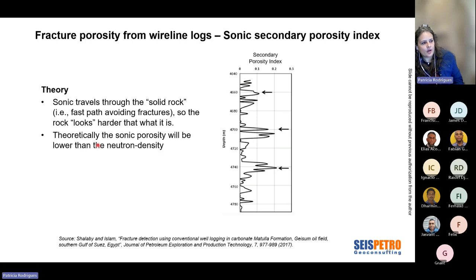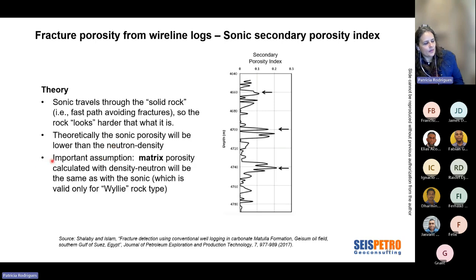Theoretically, the sonic porosity will then be lower than the neutron density porosity in the presence of fractures. It will also be valid if you have vuggy porosity as well. So anything that is isolated, the sonic log will go through the hard part and will avoid that. The important assumption that we have here is that the matrix porosity that you can calculate with the neutron density logs will be exactly the same as the sonic log, which will only be valid for certain rock types.